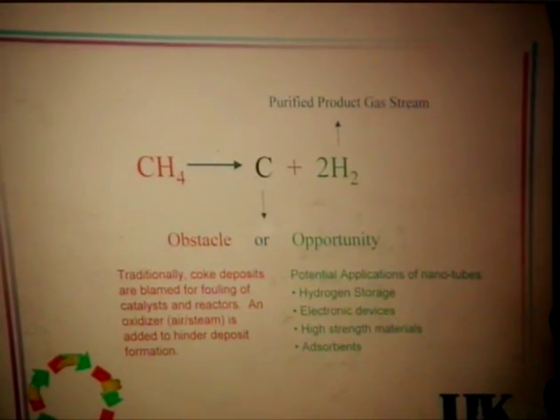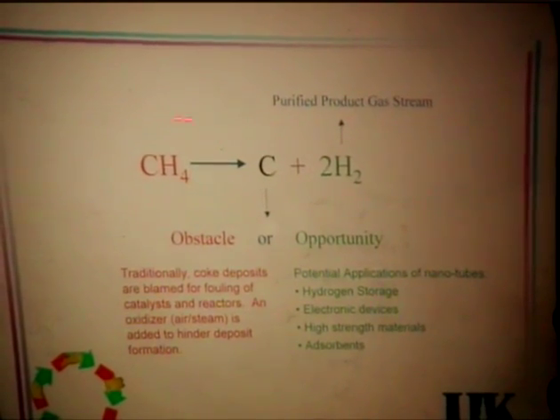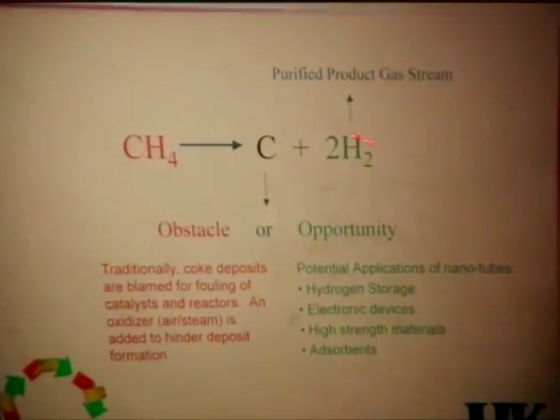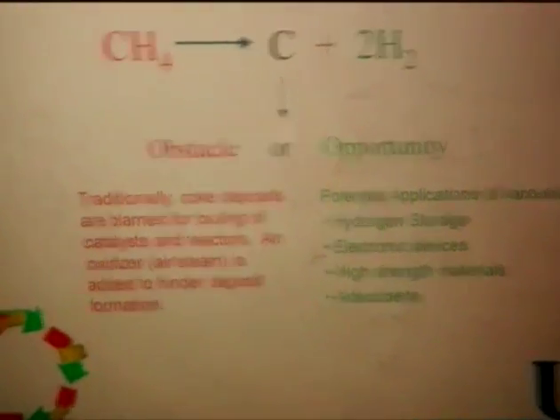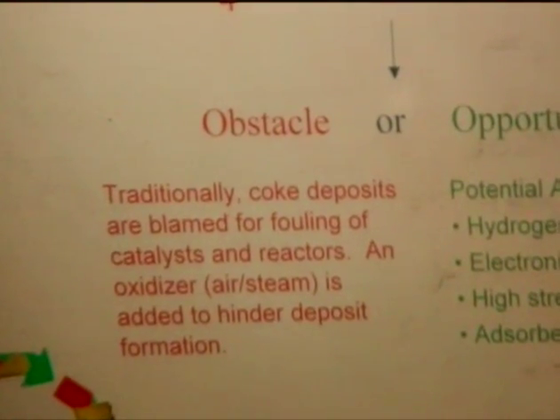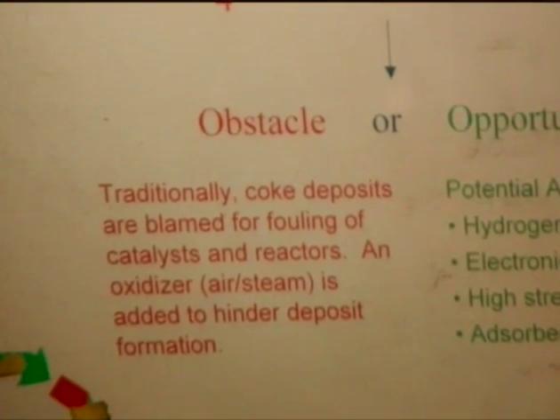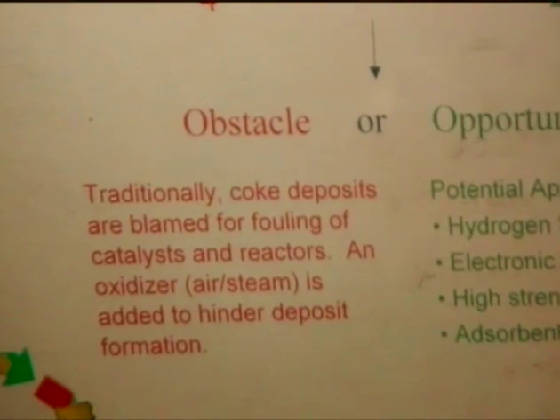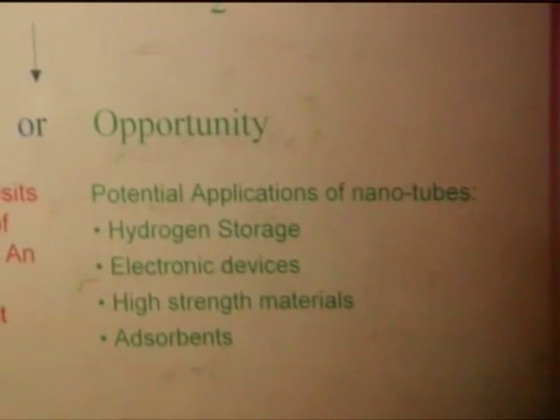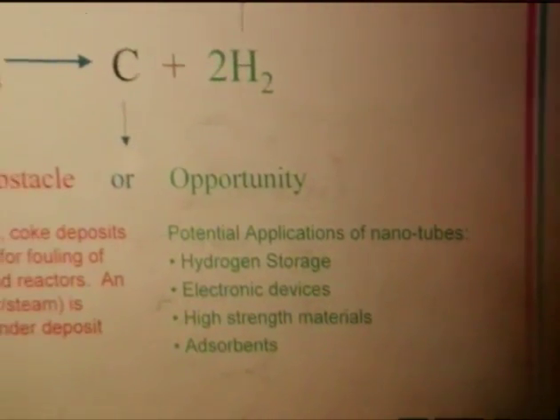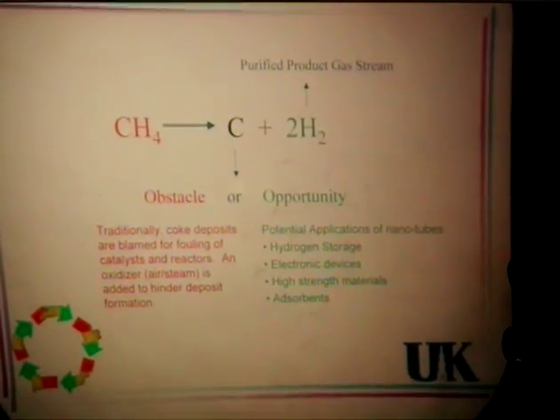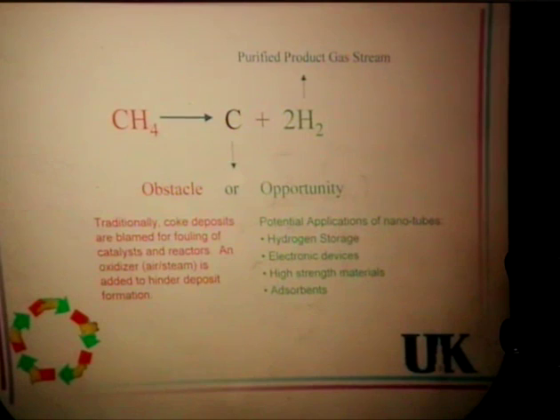Basically, in methane non-oxidative decomposition, methane decomposes into carbon and hydrogen. We are not producing any CO and CO2 in the reaction. That means we are producing a pure product gas stream of hydrogen plus carbon. Carbon is traditionally a coke deposit, the cause of fouling of the catalyst, and an oxidizer is used to hinder the deposition of coke.